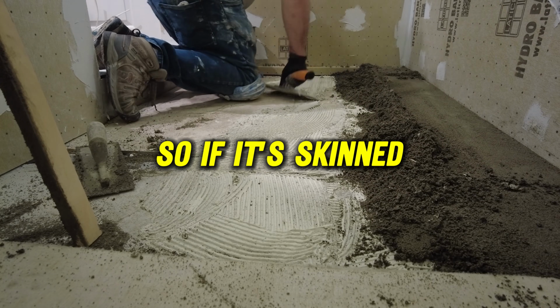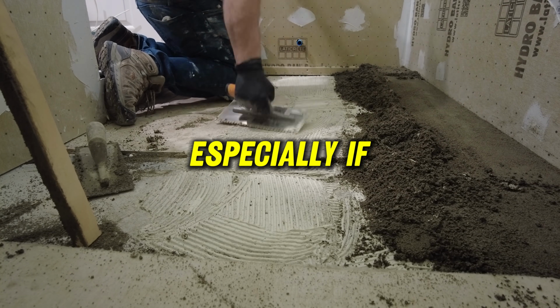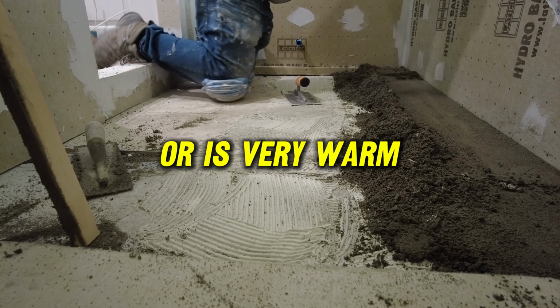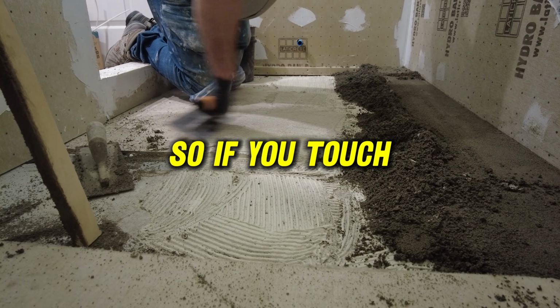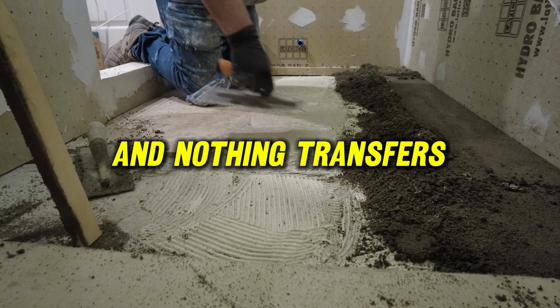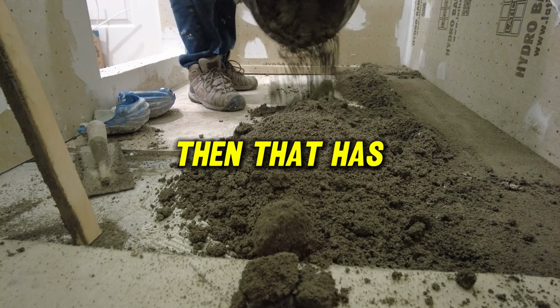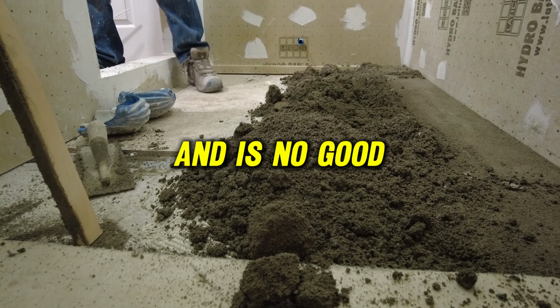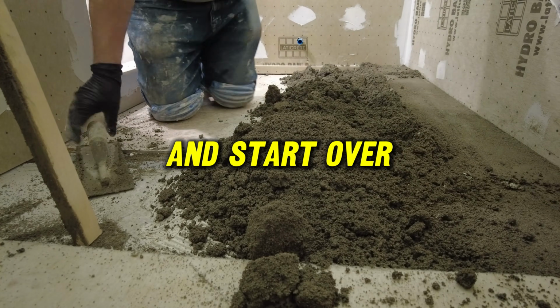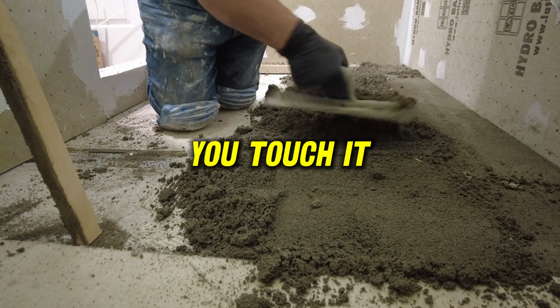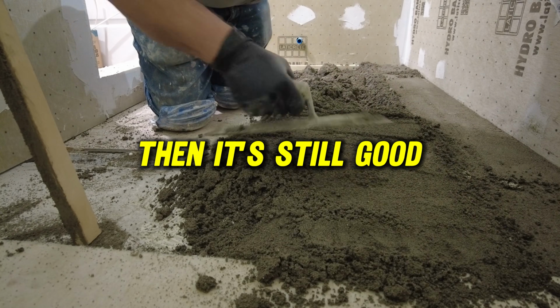So if it's skinned over, it can happen very easily, especially if you've got a fan blowing or it's very warm. What does that mean? If you touch the Thinset and nothing transfers to your finger, then that has skinned over and is no good. You've got to remove it and start over and spread some more Thinset. If you touch it and it transfers to your finger, then it's still good.